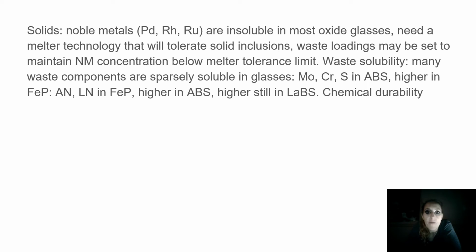Solids: noble metals are insoluble in most oxide glasses, so we need a melter technology that will tolerate solid inclusions. Waste loadings may be set to maintain noble metal concentration below the melter tolerance limit. Waste solubility: many waste components are sparsely soluble in glasses.